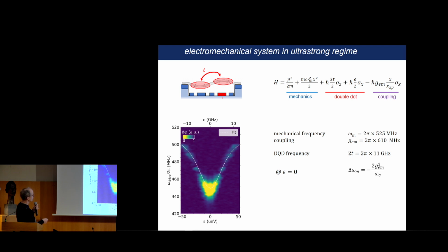And we observe a dramatic reduction of the mechanical frequency when we tune the energy difference between the left and the right dot. And from this reduction, we get a coupling strength that is larger than the mechanical frequency, so that we are again in the ultra-strong coupling regime as for the first experiments that I discussed.